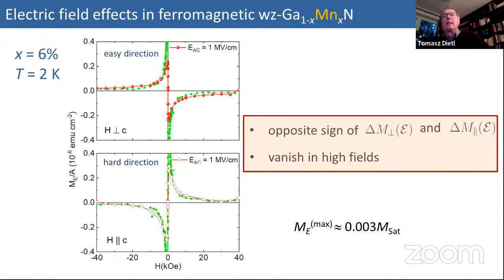Now we turn to ferromagnetic gallium manganese nitride. We know that by increasing manganese concentration, we can make this material ferromagnetic. And you see here again this electric field induced magnetization as a function of magnetic field. The red points are experimental. And depending on whether we apply the magnetic field perpendicular to the C-axis or parallel to the C-axis, we see different sign of this piezo-electromagnetic effect. And for your information, the size of this effect is something like 0.3% of saturation magnetization.